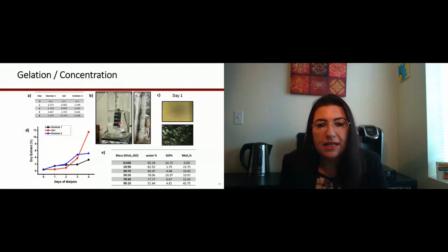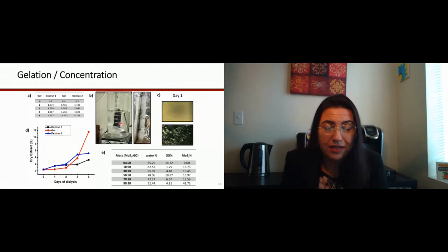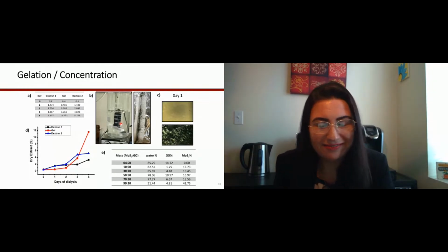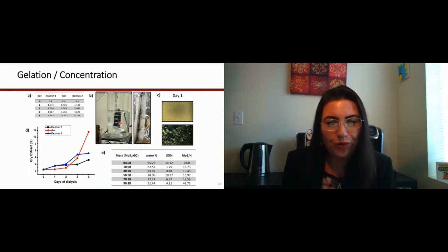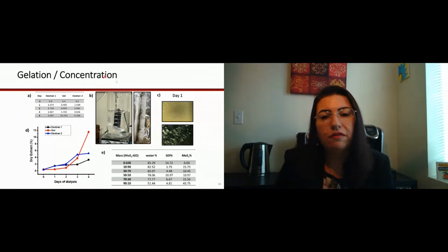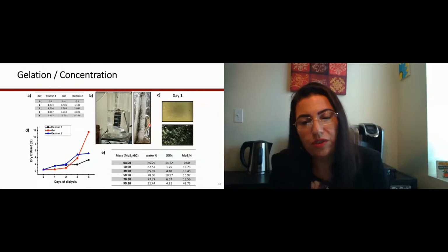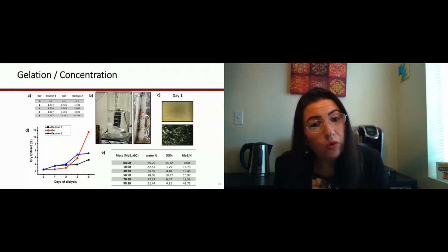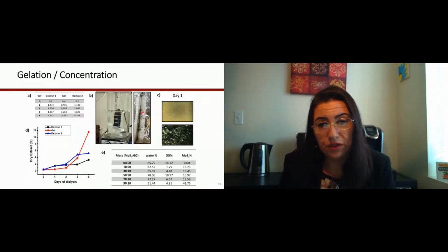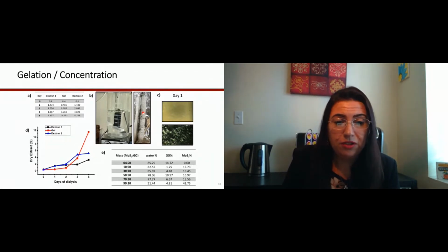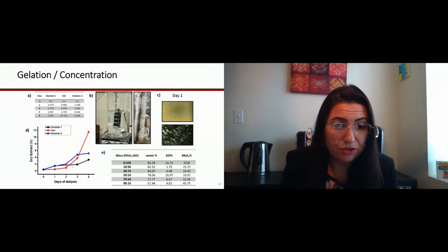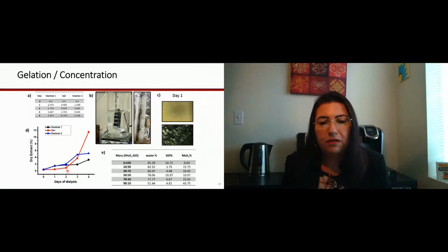The problem is that I had just 3 months in France. I didn't have time to spend 1 week to just obtain one gel. So the first novelty of our process was using this absorbent gel, where we cut the time to about 4 days for some of the materials, and for some of the materials I was able to get it in 2 days, as you can see here in the bottom.